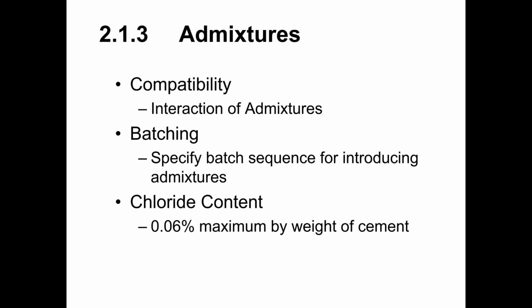As long as a plant is using admixtures from the same admixture supplier, usually compatibility is not going to be an issue because their admixture rep will give them guidance. But if for some reason the plant is using admixtures from different admixture suppliers, that increases the potential for interaction between those admixtures. All right, the batching sequence can affect the performance of the admixture.